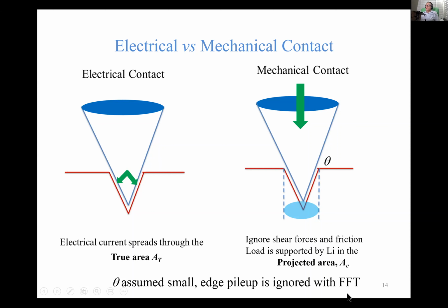Now, I mentioned that we're using this FFT technique, and there are some drawbacks that you get when you try and take advantage of the enormous speed up. One of those drawbacks is that it's valid when theta is very small. And also, when you indent lithium, where does that lithium go? It piles up on the edges around here. This FFT approach ignores that, and so it doesn't conserve lithium. So, those are potentially very significant drawbacks, penalties that you have to pay in order to get the speed.